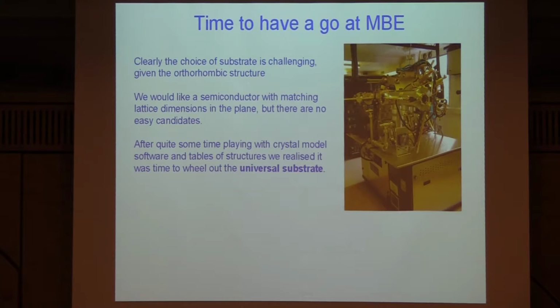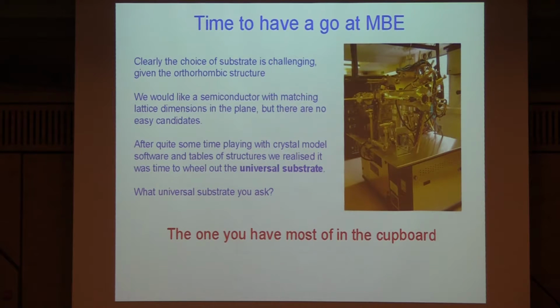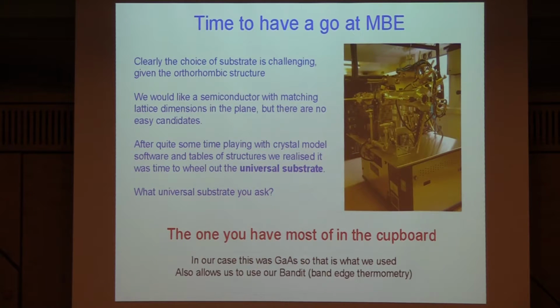Now, you guys are probably thinking, hang on, how come the growers didn't tell us about this universal substrate? Well, they know, the growers know, that the universal substrate is, well, what is it? It's the one you've got most of in the cupboard. Well, I had a look in my cupboard, and my cupboard's full of gallium arsenide, so that's what we decided to grow on, basically. That's the best way. So, in our case, gallium arsenide, and it also allowed us to use our band edge thermometry, which gives us very accurate readout of the temperature, so it was really quite a good idea to use this. But it's not the right crystal structure if you want to grow the orthorhombic. There's no question about that.